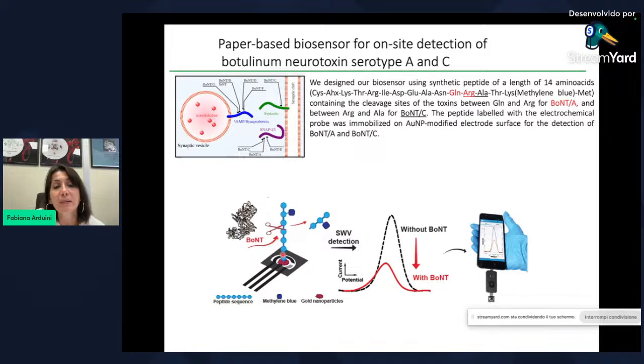peptide. If botulinum toxin A and C is present, there is cleavage of the peptide sequence, and so we remove the electrochemical probe, methylene blue, from the electrode surface, and we have a decrease of the response. So this is the approach.